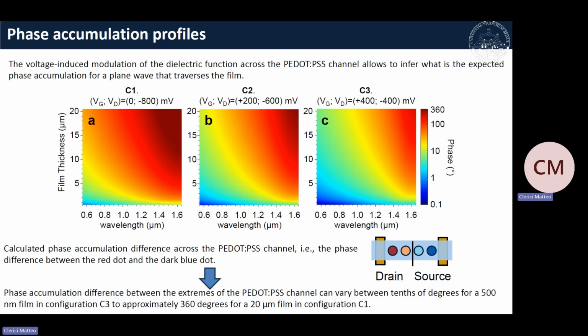So the next question was, okay, what can we do with that? This is not a metasurface, so we cannot control the refractive index at the nanoscale level, but still we can make some phase accumulation, because if I create the refractive index profile, I can accumulate some phase and create, for example, a lens. So we wanted to understand how much phase we could accumulate. Between 600 nanometers and 1.6 microns, we tested several thicknesses and several voltage configurations, and we can see that depending on the electrode configuration and thickness, we could achieve pretty much the phase accumulation that we want.